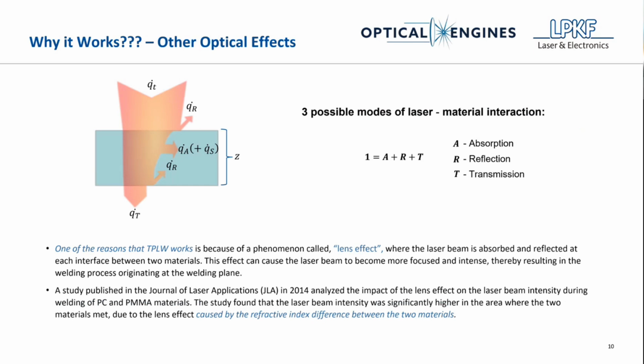Another key point as to why this works is what I would call lens effect. Technically, it's not really the right term for it, but there are basically three possible modes of laser to material interaction: absorption, reflection, and transmission. So we're getting a kind of culmination of all of those happening inside the pieces of plastic. And where there are two pieces of plastic together, we're getting the majority of these activities in the weld joint area. And you can read there was a Journal of Laser Applications study that was done on this, and it definitely showed that the beam intensity was higher in the area where the two materials met due to lens effect. And this is caused by the refractive index difference between the two materials.